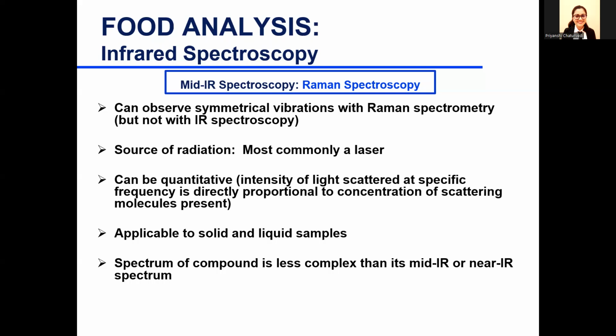So what I did for my PhD is I used IR and Raman to quantify sucrose and to identify not only the percent sucrose in a system, but was it crystalline sucrose or amorphous glassy sucrose. So I was able to, with very straightforward, simple linear regression, do that in IR. But I needed to have a multiple linear regression in order to quantify in Raman, just because of that little uncertainty of not only the energies, but then also crystal morphology was kind of messing things up a little bit because it scatters light a little differently.